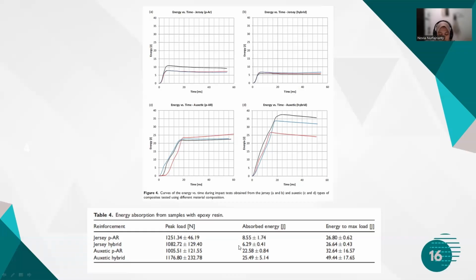The use of PA yarn in the composition of the hybrid knit fabrics did not significantly influence the energy absorption result when compared to specimens produced with para-aramid in both types of patterns, considering the mean values and standard deviation obtained. This fact may be important for the use of the hybrid fabric developed as reinforcement in composite materials with low weight along with a lower cost.